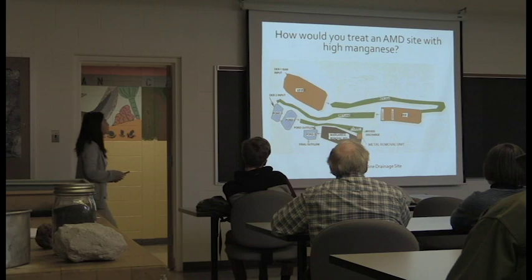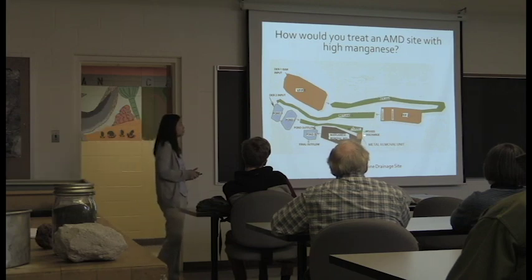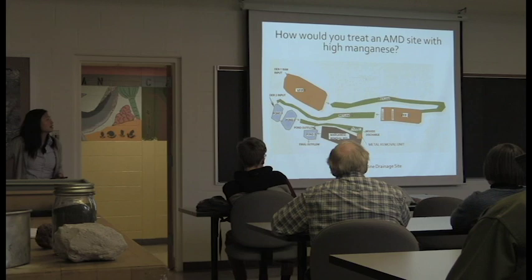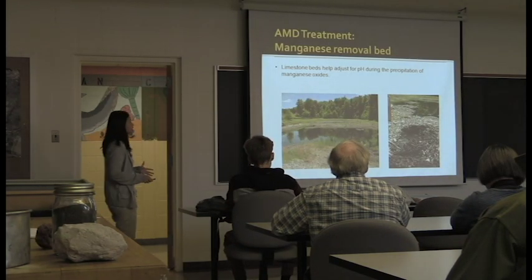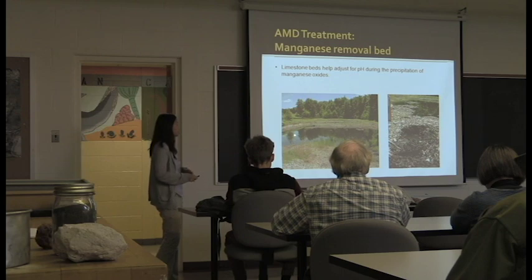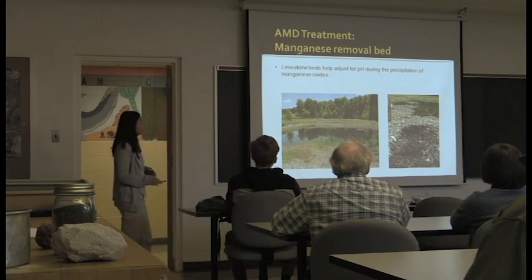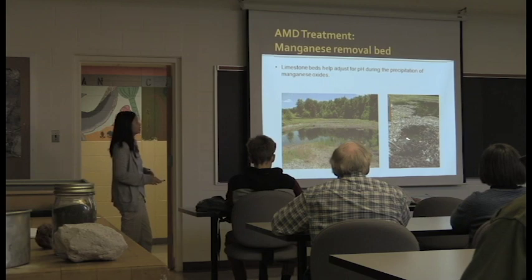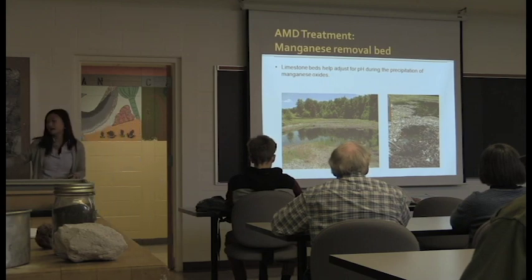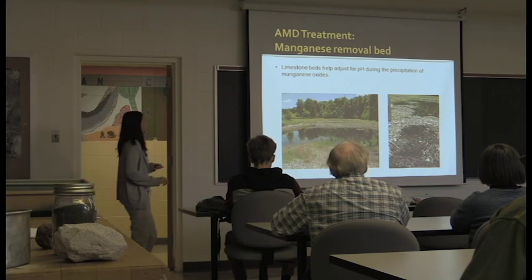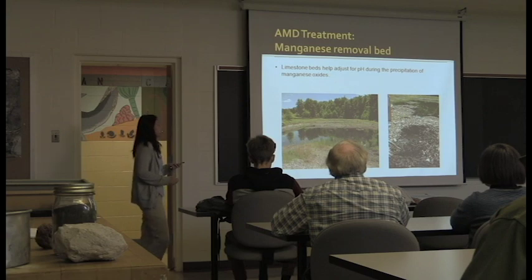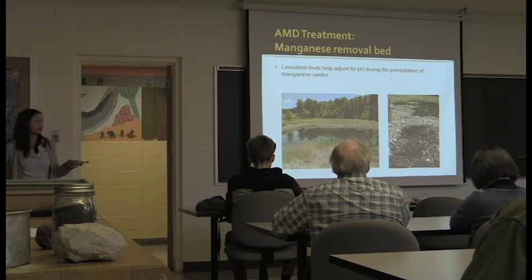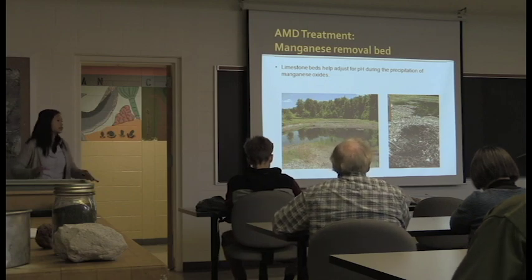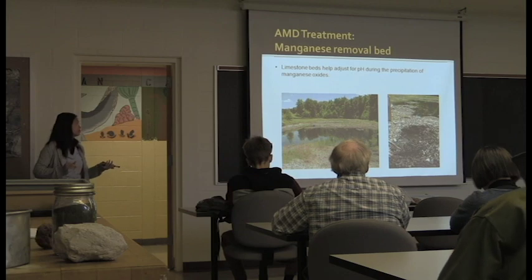The other unit we use in this system is a manganese removal bed. So there's your metal removal unit with your coconut coir, and here's your manganese removal bed. A manganese removal bed is a lot like your vertical flow pond, where you just have this humongous piece of land with lots of limestone in it. All of these are limestone. You can see there's vegetation growing on it, and there's water coming through. If you dig a hole in these limestone beds, you see that the water is just really, really black, and that's because of the manganese oxide precipitating out. Here the limestone is adjusting the pH, making the system more alkaline and further allowing that other aspect where we need a high pH to promote the precipitation of manganese oxides.